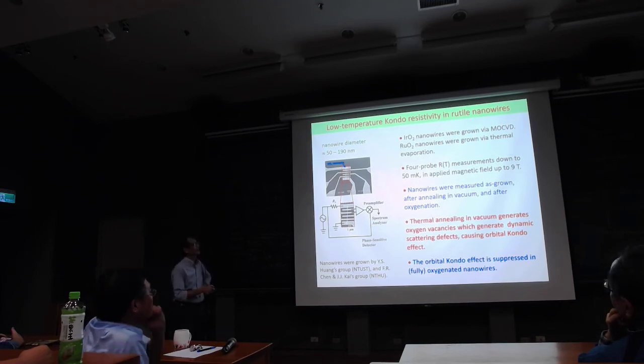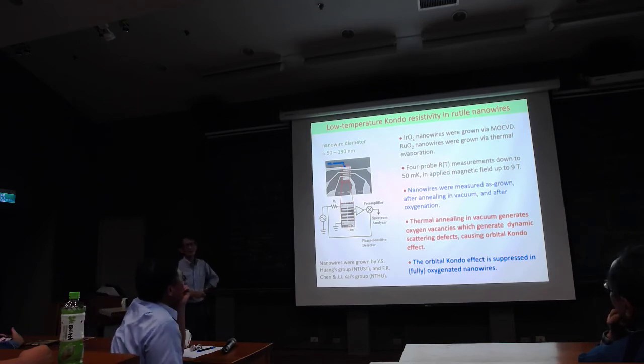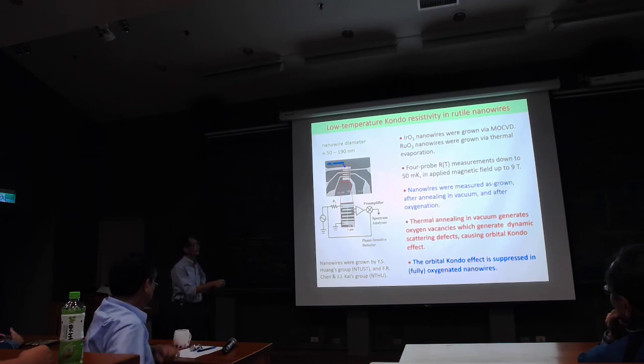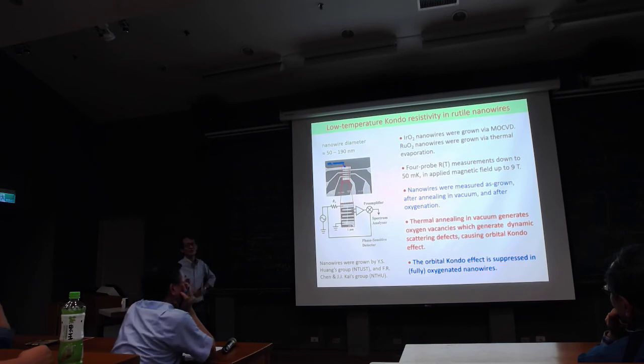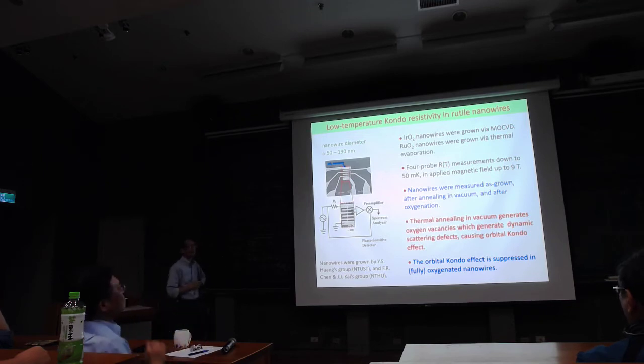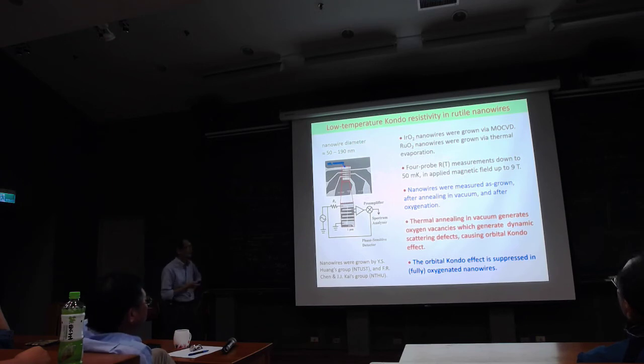And okay, this is just to say that we measure these wires when there's no oxygen vacancy, and when we take some oxygen out, so there are oxygen vacancies. And by controlling the oxygen vacancy, we can have a residual resistivity, or we can observe Kondo resistivity. So this is the experiment.